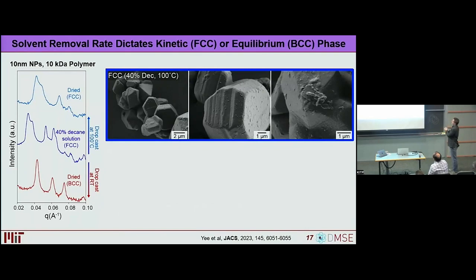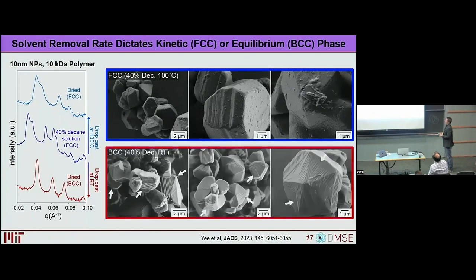If we look at the FCC case, we see a couple of interesting features. Firstly, you'll notice that they have sort of this quasi-hexagonal morphology. This is what we would predict from an FCC type lattice. There may even be some stacking faults. It's a little bit difficult to tell. The other thing, this is not the greatest image, but in this flash drying process, these particles and aggregates tend to coalesce. But if you look carefully, you can see sort of this five-fold pentatwinned structure. This is a common structure in FCC nanoparticles, things like gold nanoparticles, you'll often see this. What's interesting is if we look at the BCC case, it's the same exact shapes.